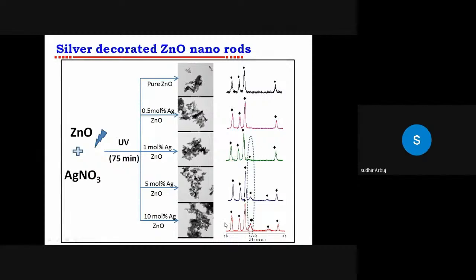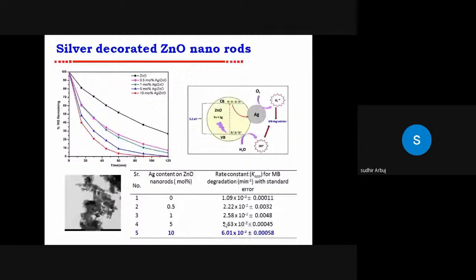And we observe this photocatalytic activity. What we observe is that as we increase the percentage of silver, we are getting higher photocatalytic activity for dye degradation. Almost in 1 hour, it completely degrades the dye. See, for zinc oxide, its activity is lower. As we increase the silver percentage, the activity increases.